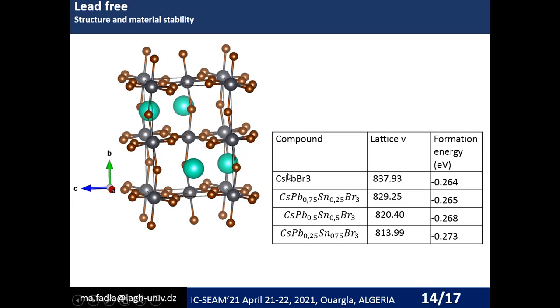So this compound, cesium lead bromide perovskite, is in the orthorhombic structure. As you can see here, we calculate the volume of this unit cell, as well as the formation energy, and you can see they have almost the same formation energy. We improve their stability a little bit, but they have almost the same energy.